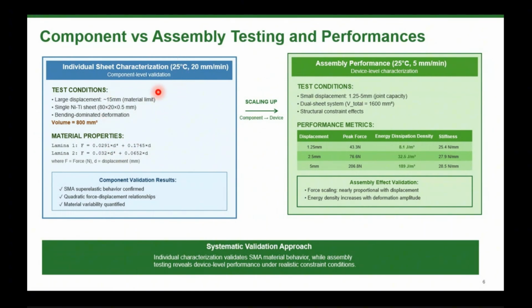What we found, let's talk first about the individual sheet characterization. We found these two experimental laws. I don't know if you are able to read, but I can tell you that we found that the sheets have a quadratic force displacement relationship. So it's true that the sheets are super elastic at ambient temperature.